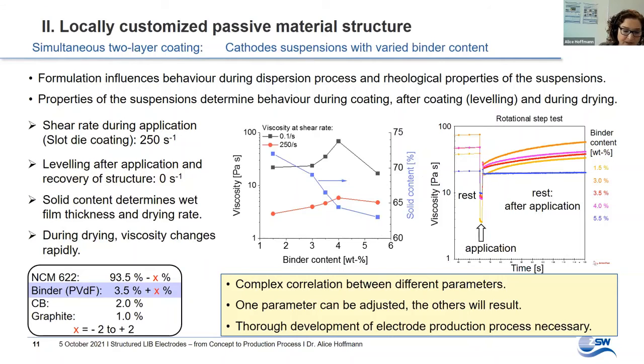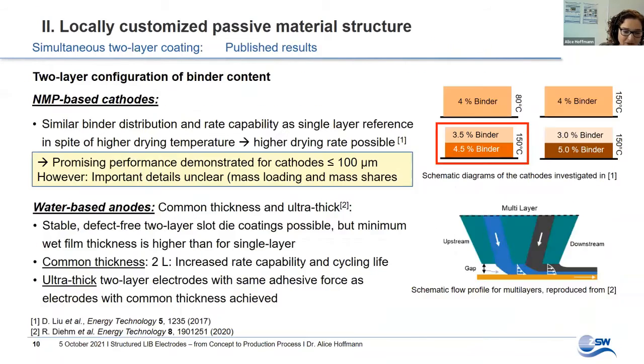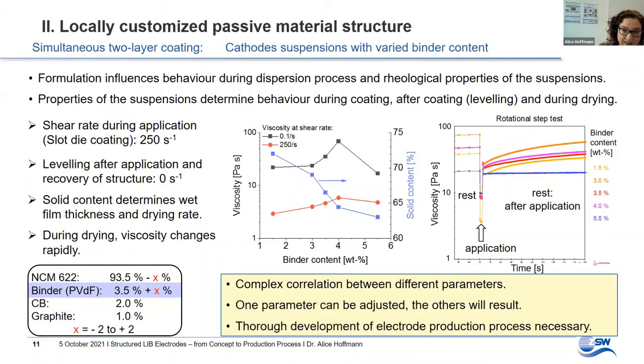However, changing the formulation of a suspension affects its behavior during the dispersion process and the rheological properties, which determine the behavior during coating, after application and during drying. For example, during the slot die coating of our thick electrodes, the suspension is subjected to a shear rate of about 250 per second. This is shown here in red.